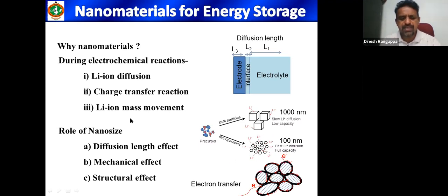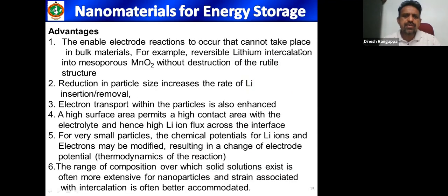So if we can do this, then nano size will help us by decreasing diffusion length, and also it supports a mechanical effect and structural stability. So nanomaterials provide some advantages when we use them in energy storage devices as electrode. The nanomaterials enable electrode reactions to occur that cannot take place in bulk materials. For example, reversible lithium intercalation into mesoporous MnO2 without destruction of the rutile structure is possible if you adopt nano size electrode material. And reduction in particle size increases the rate of lithium insertion and removal, as I explained in the previous slide. The electron transport within the particle is also enhanced.